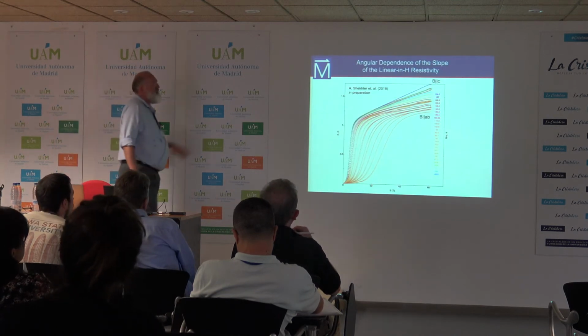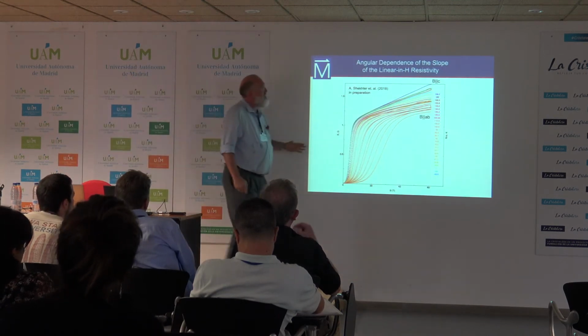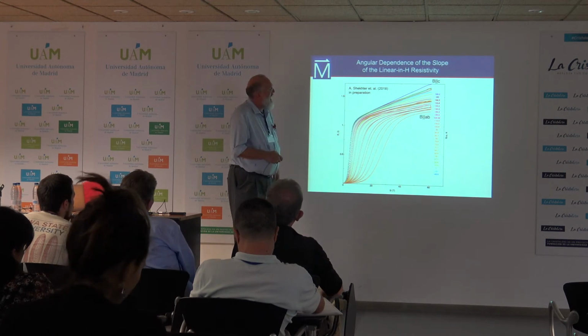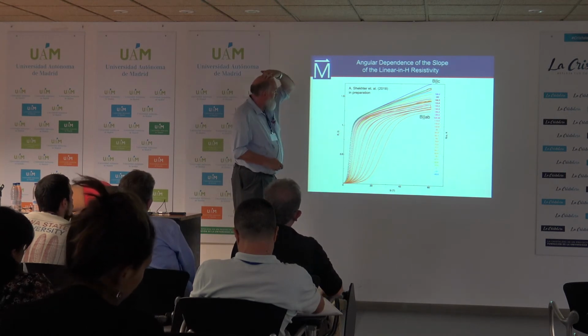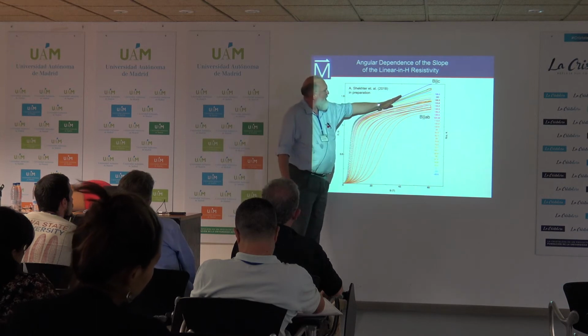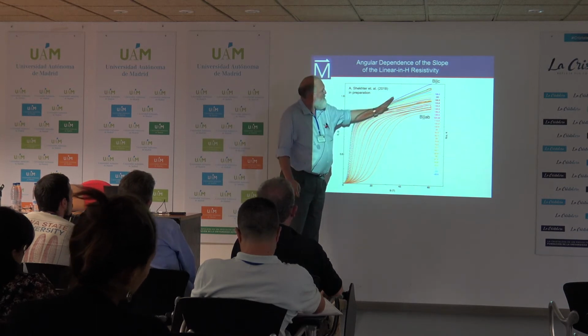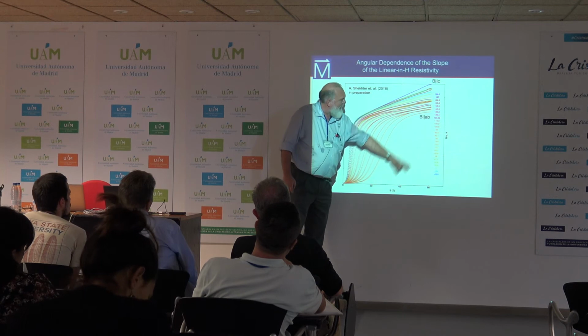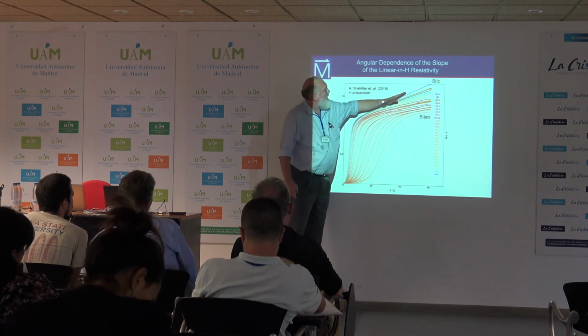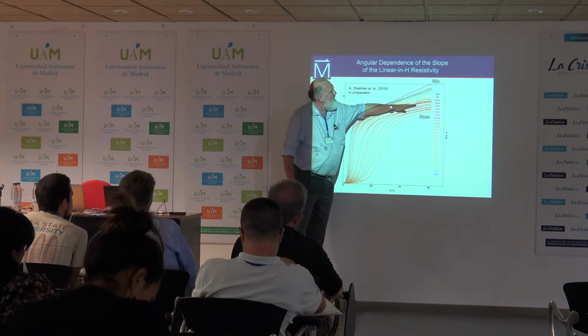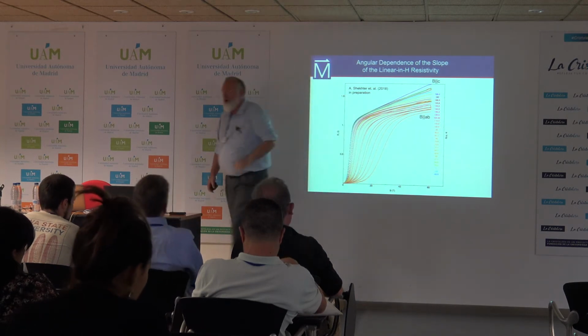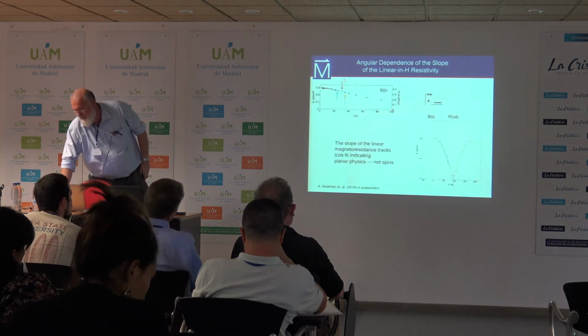Okay, so then the question is, how does that linear coefficient change as a function of angle? And Arkady Shekhter is working on a manuscript where he rotates the sample. As you put the field more and more in the plane, you run out of field more readily, but you're plotting this slope as a function of orientation of the magnetic field from along the c-axis to in the plane.